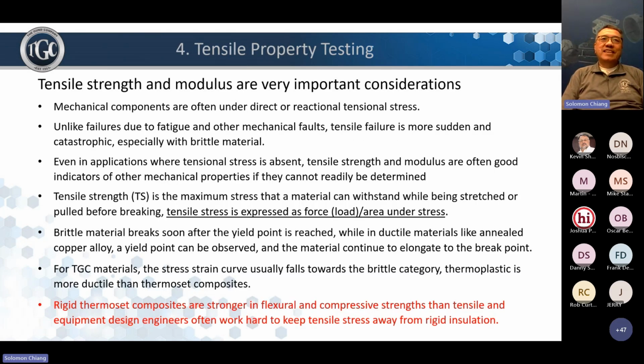This one, I think one of the reasons why NEMA or IEC do not put it into their spec as a requirement is that this is one property a design engineer tries to avoid as far as the insulating material is concerned, because rigid thermoset laminate, the insulating material used for mechanical support, is always stronger in flexural and compressive strength than in tensile. So most design engineers will want to make sure that the insulating material is not under tensile stress. So this property is obviously very important for design work.